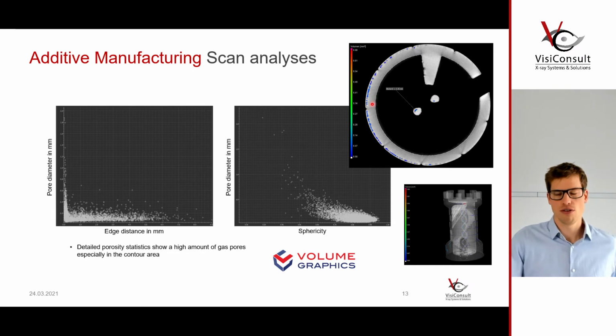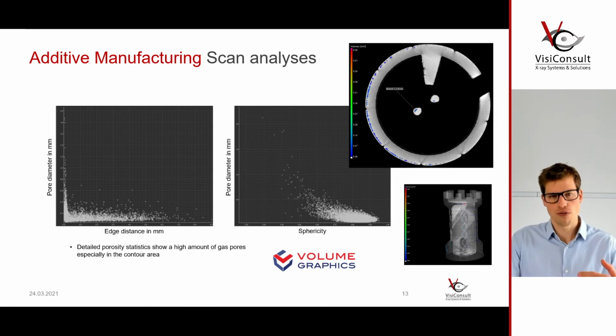So this is very important, especially as additively manufactured parts have a quite high surface roughness. So it's very likely that you want to surface treat it, either way mechanically or chemically. There are different ways you can do this. But by doing so, you would remove the first layers of the part. And it's very likely, at this part especially, that you open the porosities.